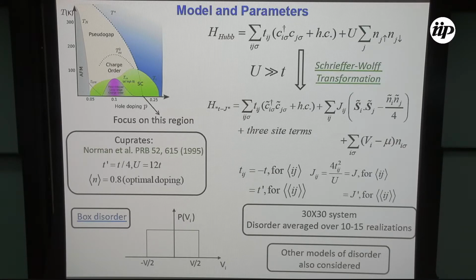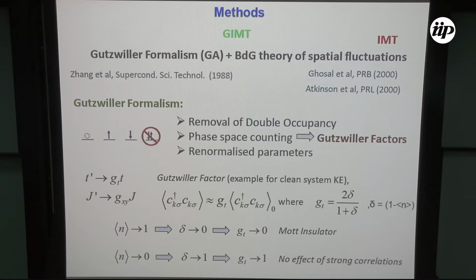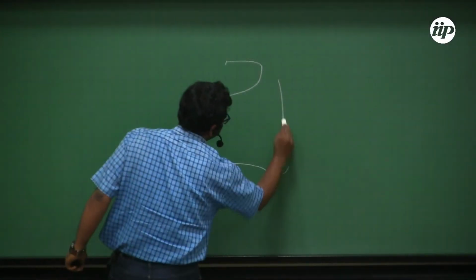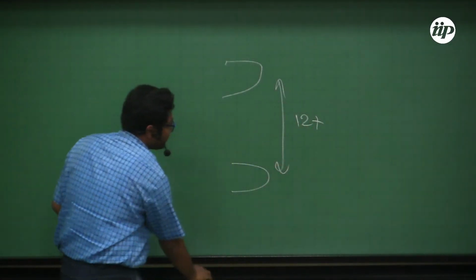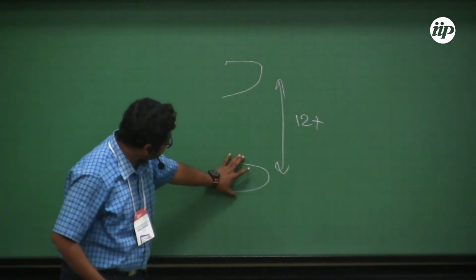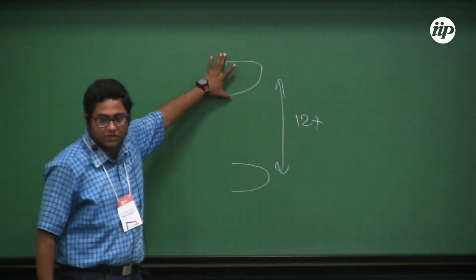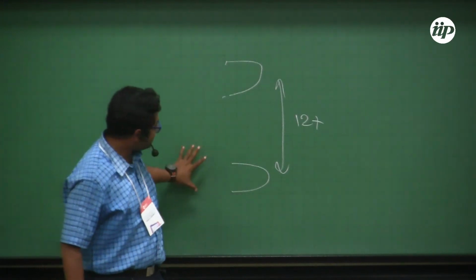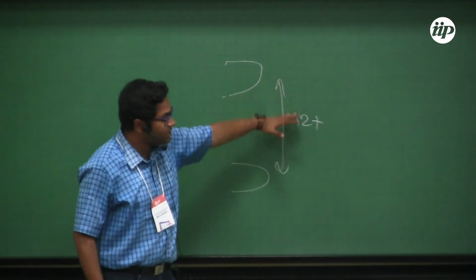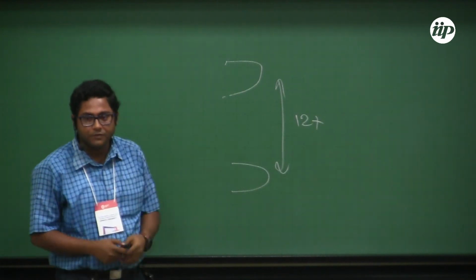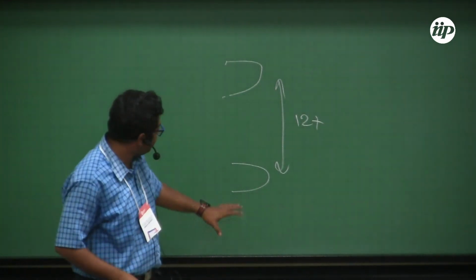So we are actually taking them out from the problem, because when we do Gutzwiller approximation, you remove all double occupancy from the system. We don't allow any partial, because 12T is large. If I show you the band, you will see that there would be two bands. This would be 12T. This band is just the single occupancy band. This is the double occupancy band. So they don't talk to each other. We are just working here. And since this is a very large energy scale, they will be out of the problem. So we want a low energy effective problem where we work here only.